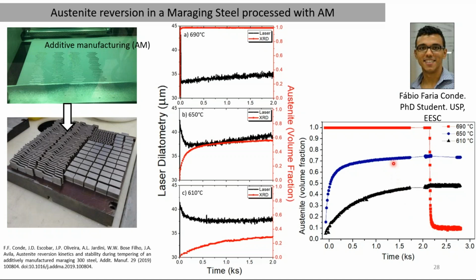And now let's see the intermediate temperatures. We can see that we reverted, in this case for the blue one, 70%. And we stabilized almost 70% of the austenite. So this austenite reverted at high temperature is very unstable and is going to change to martensite, but intermediate temperatures are going to work better.